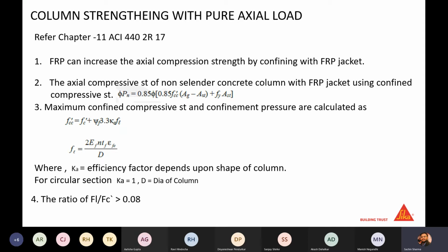by confining the column. The capacity of the column post confinement will be given as 0.85 times of this formula, and this is limited to the cross section of the area, because FRP contributes very well for circular columns. If it is a rectangular column, the contribution will be less. So that is why an additional factor of contribution, which is a shape factor, is applied in the case of rectangular columns, whereas for the circular column, the formula is the same, which is shown here, where D is the diameter of